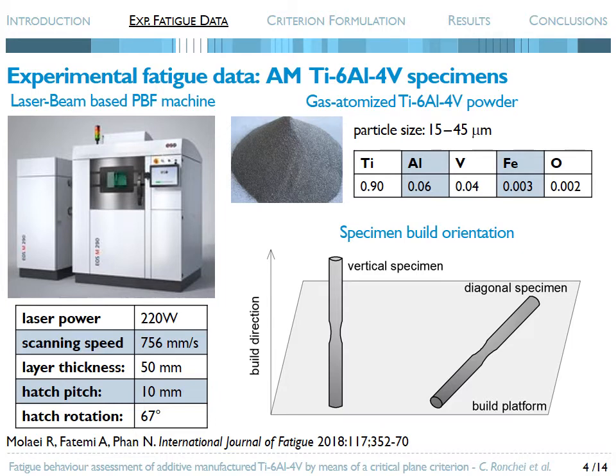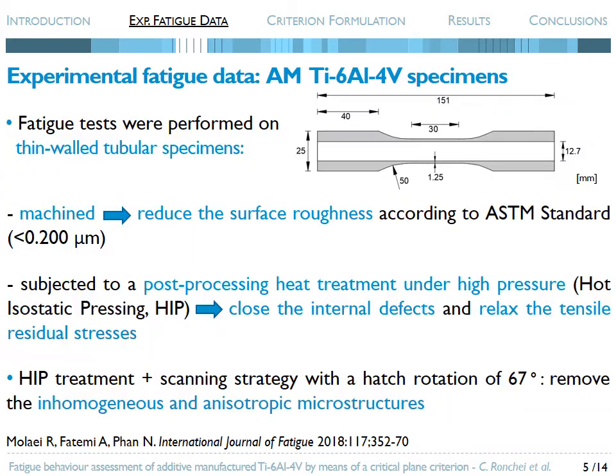The material employed in the manufacturing process was a gas atomized Ti-6Al-4V powder with a particle size range of 15-45 micron. The chemical composition of such a powder is reported in the table on the top. The specimens were built with an orientation of both 90 degrees, named vertical specimens, and 45 degrees, named diagonal specimens, with respect to the build platform.